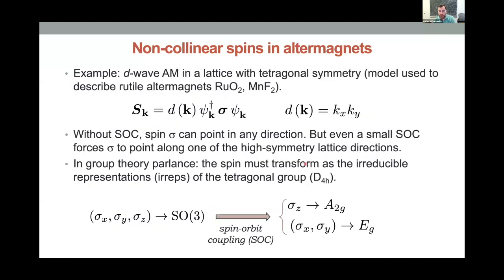So to give you an example of how this happens, consider the case of a rutile, for example, manganese difluoride. It's a tetragonal lattice. I put a d-wave form factor here, kx ky. Okay? If I turn on, without spin-orbit coupling, the spin transforms as irreducible representations of SO(3) or SU(2). But when I turn on spin-orbit coupling, they will actually have to transform as irreducible representations of the tetragonal group. So if the spin points along the z direction, it is A2g. If it's x and y, it is Eg.